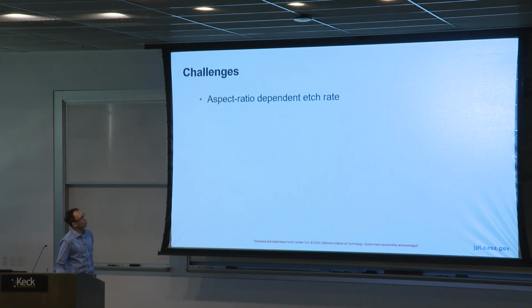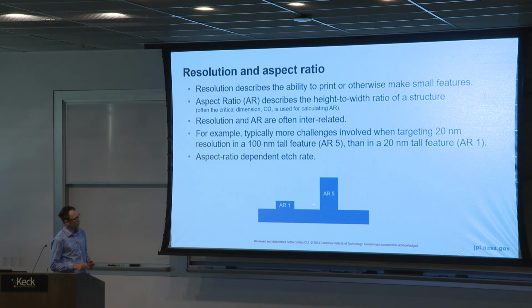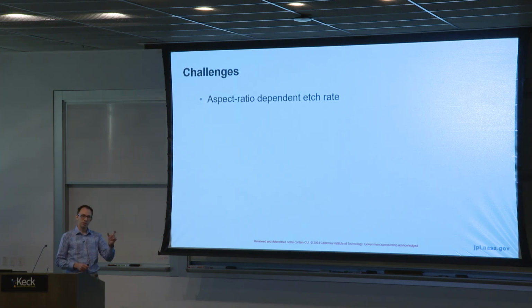So this is a problem for, I would say, most types of etching that you want to do. If you have a situation where your features have different aspect ratios, and even if the gaps are... that's actually a very bad example because it's mostly the gaps that are different. So let me do this instead. If you have a gap that's a few microns wide and you have another gap in your surface that's only 100 nanometers wide, typically the wide gap is going to etch much faster than the small gap, meaning that you will end up with a situation where your metasurface is not uniformly deep. You have patches which are very deeply etched and other patches which are not etched very deeply at all. There are definitely ways to get around that and mitigate those effects, but it's always going to be there, so it's hard to completely solve that issue.